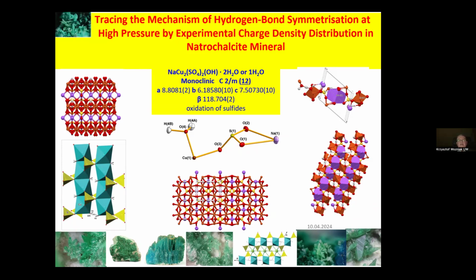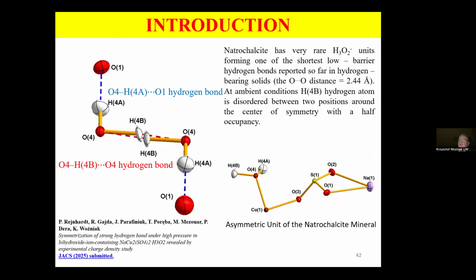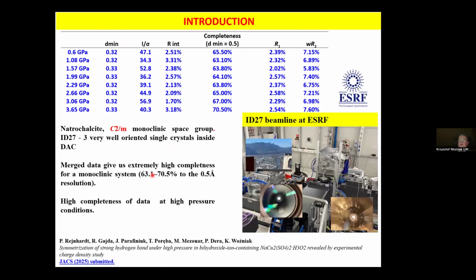There is something very interesting here. The key point in this mineral is bihydroxide unit, which is defined here. We have very strong, very short hydrogen bonding between two oxygen atoms with this H4B hydrogen atom. And additionally, those oxygens, they form rather routine hydrogen bonds to other oxygens in these crystals. A lot is going on in this hydrogen bonding.